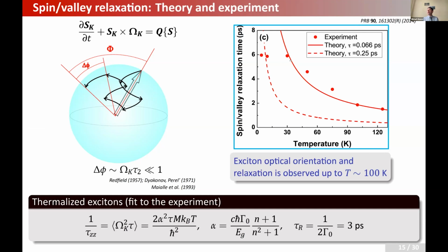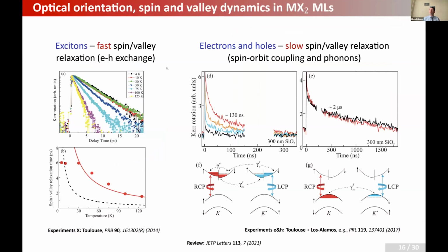The points are the experimental data, and these curves are model calculations within the kinetic equation model for the exciton spin density matrix. You can get reasonable agreement between the theory and experiment, depending a little bit on the parameters of the structures. It was about 10 years ago. The quality of samples was not very high. The scattering rates were probably a little bit too high, but nonetheless, you can observe exciton valley orientation. You can observe its relatively fast depolarization on the time scale of several picoseconds. And actually, this is the effect of the exciton long-range exchange interaction, the exchange interaction between electron and hole. This is one of the specific features of these transition metal dichalcogenides.